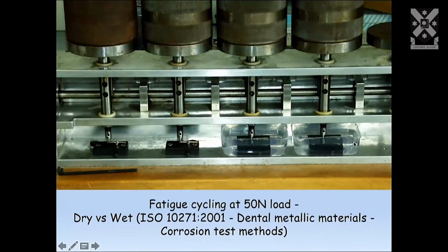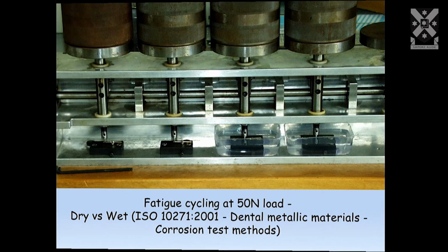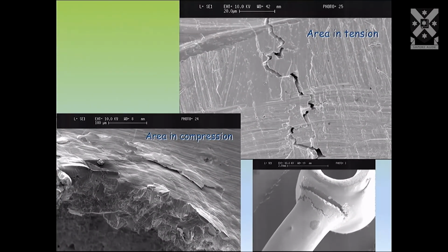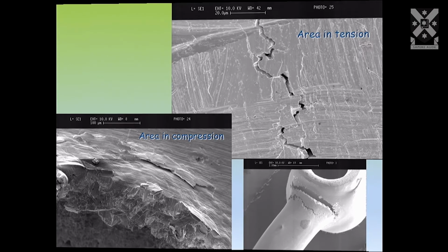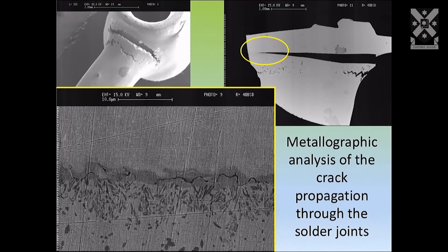Running parallel to that, we said, well, let's fatigue cycle these. In the aircraft industry, when a plane falls out of the sky, they will often do these types of tests. So we ran 2 in a dry environment and 2 in a wet, corrosive environment, and we cycled these until they failed. At different stages, we were able to take them out, look at them under the microscope, and see the progress of what was taking place, until we got failure of the solder joint. Once they failed, we embedded them and again cut them through. We cut them lengthwise like this, and then polished them up to look under the microscope.